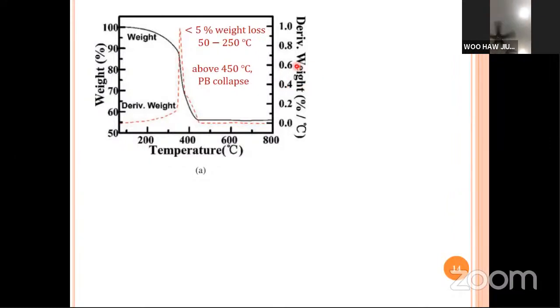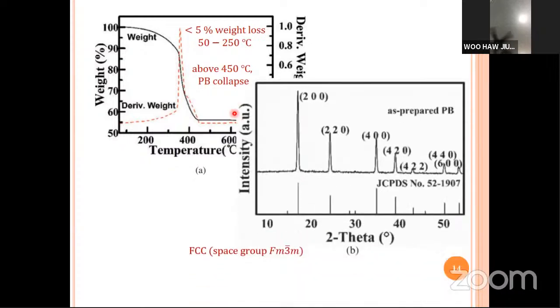If you look at it, between 50 to 250 degrees C, there is a drop of about 5%. Basically, this weight loss is due to the water content inside the material. And above 450 degrees, we observe a PB collapse. They start to collapse and decompose.